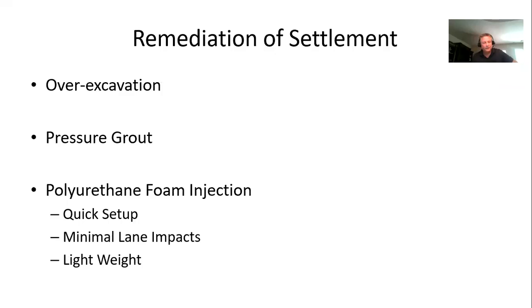Now, obviously, polyurethane is very light, extremely light, and the other great thing I really like about it is that it's a closed cell composition. It doesn't take on water once it's injected. You can cut a cross section through it and it might look like a sponge, but with a closed cell, it's really not letting any water get within it. And so it's not gaining weight over time. It just finds its way into voids. And believe me, there were a lot of voids out there. We pumped a lot of grout, but you can go into that later.